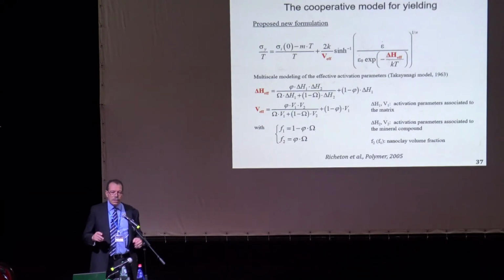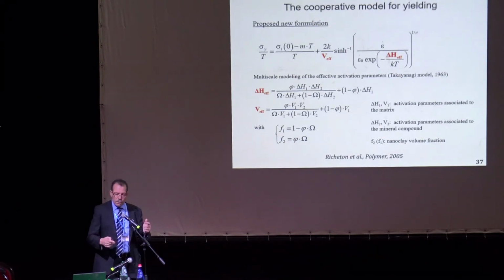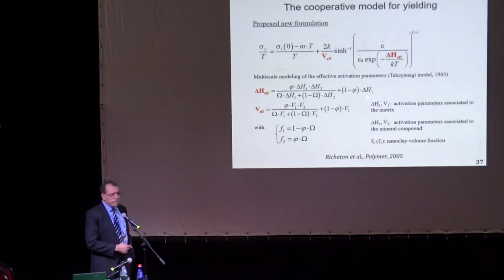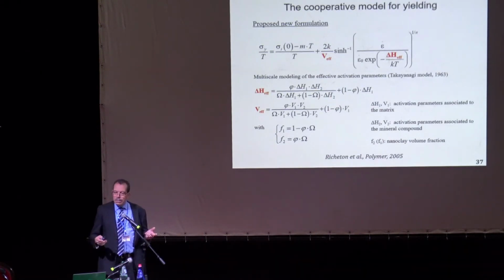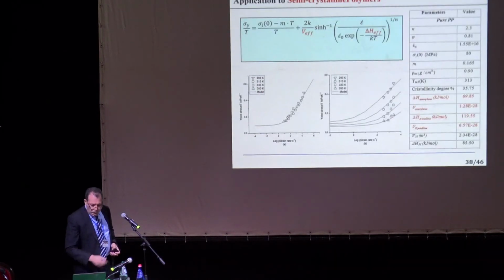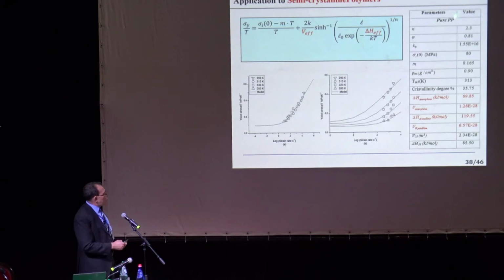Now, if the matrix, your polymer, is all amorphous, well, this is V and this is delta H. But if it is a two-phase, it could be semi-crystalline, or it could be amorphous plus nanoclay. And if you assume nanoclay deforms plastically, okay, like the crystals of the polymers, then we have to homogenize to calculate the effective activation energy, the effective activation volume. Okay, so in this we don't have to go through. This is a one-dimensional thing. Okay, and we can use a simple averaging, upper bound, lower bound. Here we use something in between. That's the Takayanagi model. Okay, and by this we used it for semi-crystalline polymers. This is an application to polypropylene. As you can see, we are predicting very nicely the yield stress as a function of strain rate, all ranges of strain rate from quasi-static to dynamic, okay, and several ranges of temperatures.